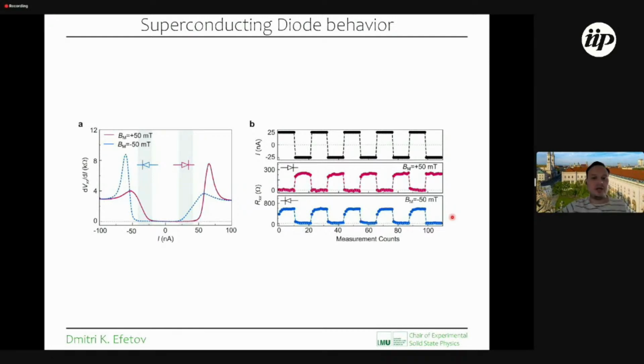And last but not least, this asymmetry of the Fraunhofer has also some practical implications. So, for example, we were able to show that a critical current in one direction can flow, whereas at the same current in the other direction, no superconductivity is observed. This is identified by these windows in current, which you can see here, where we can switch by applying a certain current direction. We can show that it is superconducting in one direction and resistive in the other direction. And of course, we can also program this diode effect by applying a magnetic field and reversing this diode behavior.